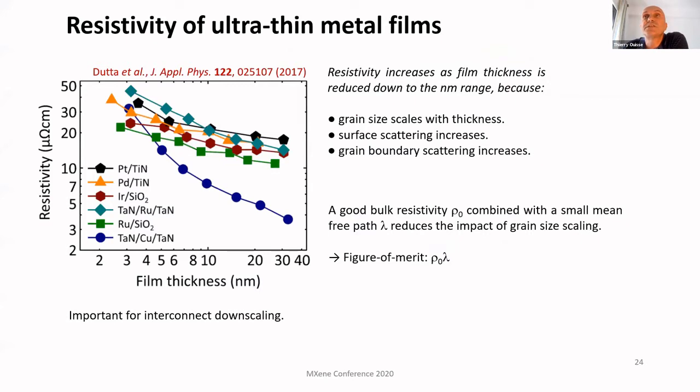Before addressing the case of our flakes, I would like to say a few words about the scaling of the resistivity of thin metallic films with thickness. It's an important reliability concern for downscaling interconnects of integrated circuits. In the case of copper lines, resistivity increases as film thickness is reduced down to the nanometer range. You can see this increase with the curve in blue on this graph.